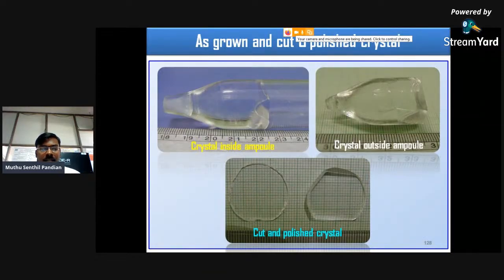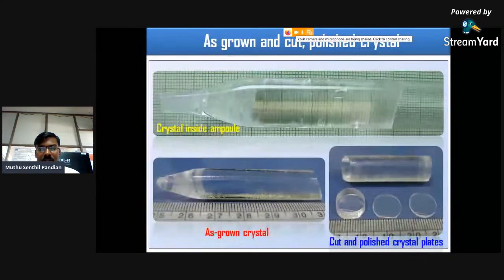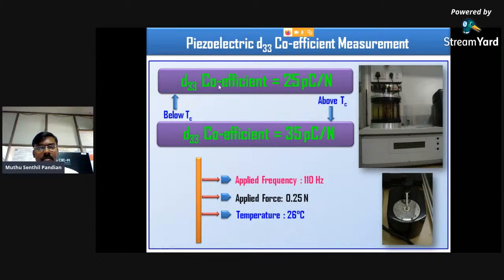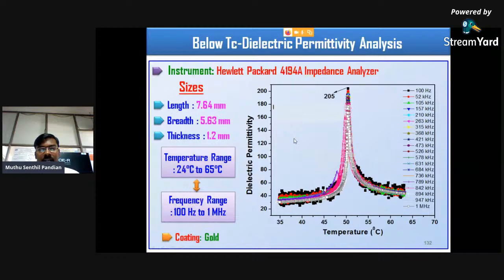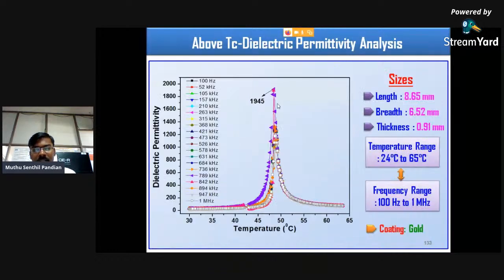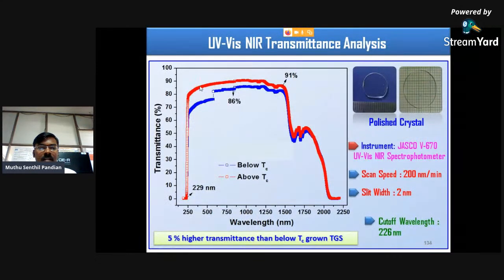We have also grown triglycine sulfate single crystals, TGS crystals, below and above TC. For curiosity, we have done this. So these are the TGS crystals in the paraelectric phase. We have compared the characterization: the piezoelectric coefficient in the ferroelectric phase is 25 picocoulomb per Newton, but in the paraelectric phase it is 35 picocoulomb per Newton. The dielectric permittivity value in the ferroelectric phase is 205, but in the paraelectric phase it is more than 1000. UV-NIR measurements have been carried out for the ferroelectric and paraelectric phases of the TGS single crystals: 86% in the ferroelectric phase, but above TC, the paraelectric phase, 91%.